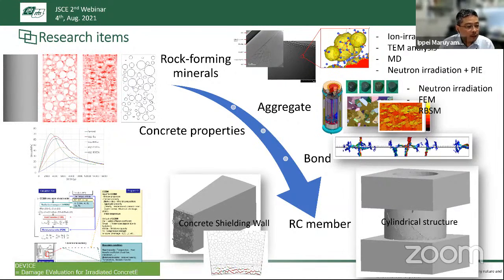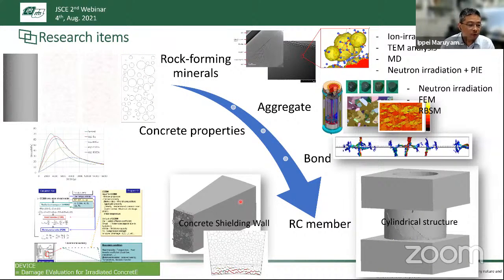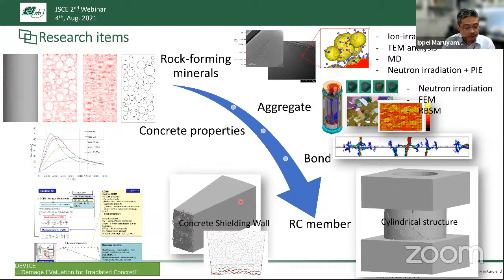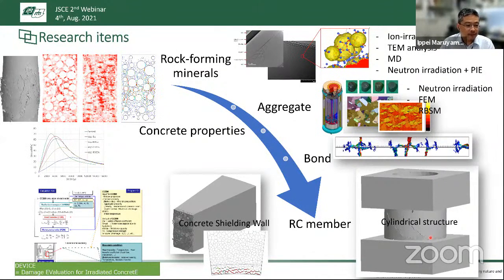And at the same time, at the aggregate level, we do the irradiation experiment. And above this size, we are doing the numerical analysis. Based on the rigid body spring network model, we can make the bridge between aggregate expansion and the degradation of the concrete properties, compressive strength, Young's modulus, tensile strength, whatever. And above this, we try to evaluate the behavior of the very thick concrete wall, which is irradiated from one side, and also try to evaluate the seismic performance of the cylindrical structure, which is affected by the neutron irradiation. So all kinds of scales are investigated currently.